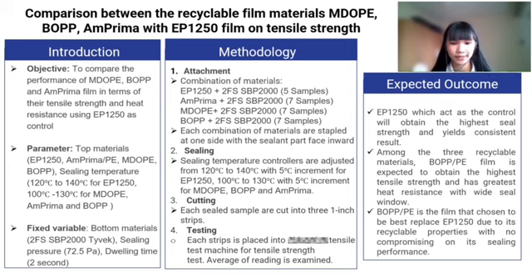So there will be a total of 7 samples prepared for each combination of recyclable materials, while for the EP1250, there will be 5 samples prepared to be sealed at different temperatures. Next, for the sealing process, the sealing temperature controllers are adjusted to the desired temperature for each pad sample, and the sealing pressure is fixed at 72.5 Pascal. Then, after the sealing process, the sealed samples are cut into 3 strips of 1 inch length by using the 1 inch cutter. Lastly, each strip is then placed into a tensile test machine for tensile strength test, and the average of reading is examined.